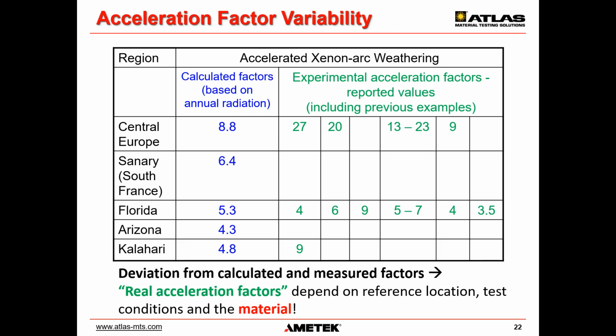From the previous examples, we can see that first, the experimental acceleration factors can differ significantly from those calculated from radiant energy equivalence and time compression in the lab exposures. Second, there is no universal acceleration factor. The factors are highly specific for both the change in properties measured as well as the material chemistry, and also for the specific outdoor and accelerated tests used.